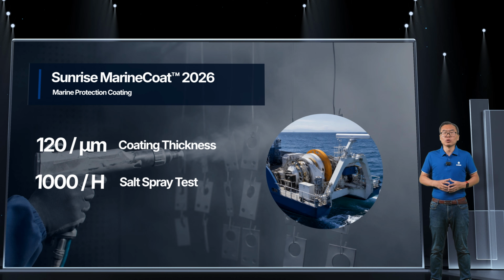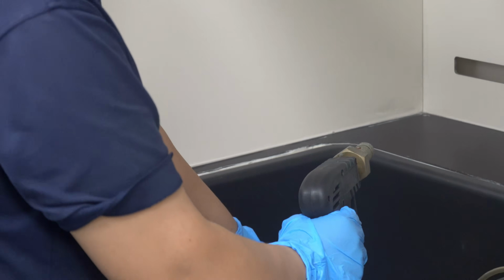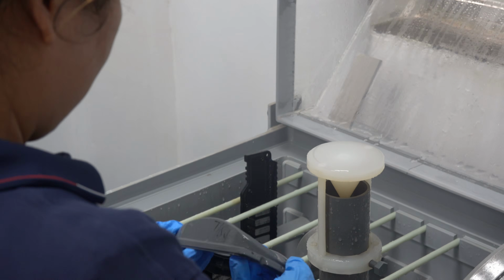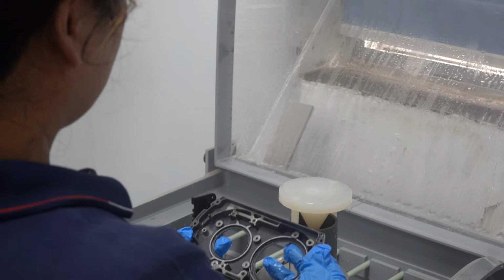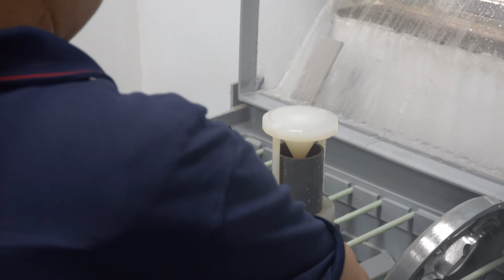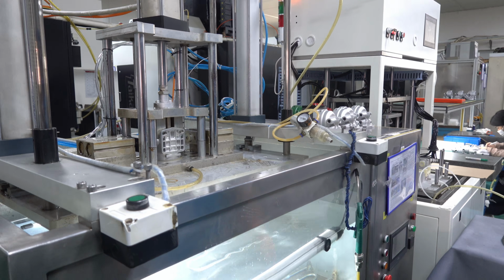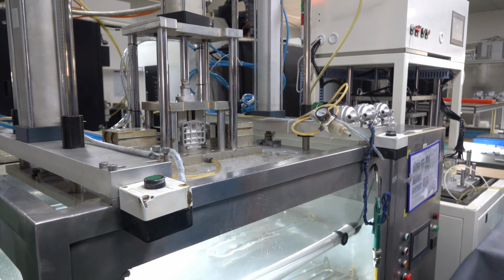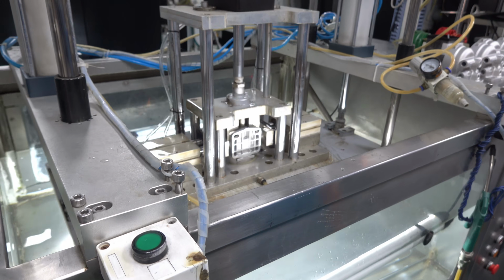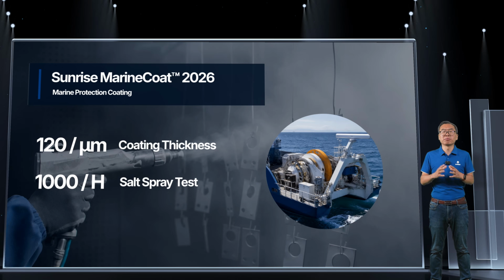Finally, we protect the outside with Sunrise Marine Coat 2026 Marine Protection Coating. Marine coating is not simply paint on the surface. It is a protection system. Pre-treatment must remove oil, oxide layers, release agent residue, and unstable surface material. The coating must protect flat surfaces, edges, holes, corners, and machined areas. For selected marine applications, our target coating thickness is 120 micron with 1,000 hours salt spray test validations.